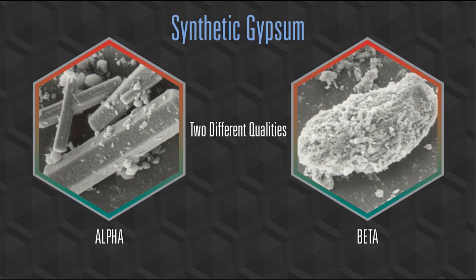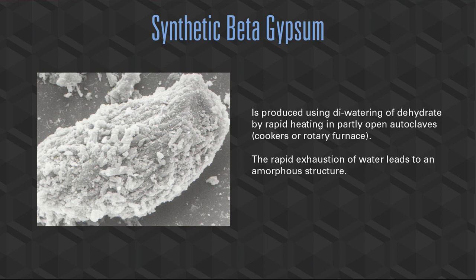Synthetic beta gypsum is dewatering of the dihydrate by rapid heating. So basically the rotary furnace or the cooker autoclave does not hold the pressure as long as we need it to. That rapid exhaustion of water becomes more of an amorphous shaped structure. Kind of imagine Q-tips. If you're stacking Q-tip on top of Q-tip, it's very spongy and you have spacing in between that product. So you're not going to get a very high PSI strength out of a synthetic beta gypsum system. So synthetic beta is very unstable.